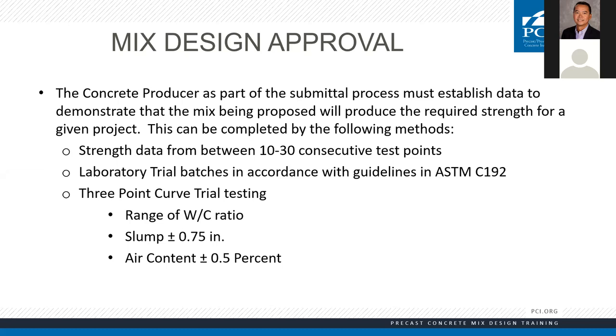As a standard, if you can get 30 individual test points, you'll be able to calculate the best possible standard deviation without the safety factor and get the lowest required design strength. The second way is laboratory trial batches, which we can conduct in accordance with ASTM C 192. If we don't have any testing from production practice, we'll do these laboratory test batches.